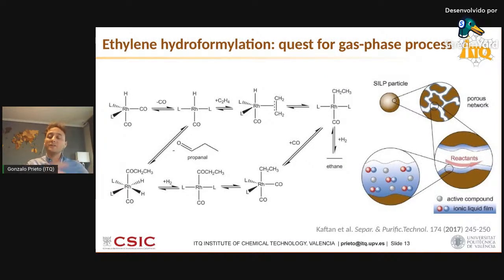Well, ethylene hydroformylation is a well-known and well-established process, but in the liquid phase. In the liquid phase and with molecular catalyst in solution, typically based on rhodium carbonyl complexes stabilized by different organic ligands. Organophosphines are one of the most common. However, for very volatile, very low boiling point olefins, such as ethylene, also propylene, developing an alternative process which is capable of operating in the gas phase and with solid catalysts is certainly attached to a number of technical incentives related to process intensification and OPEX savings, for sure.